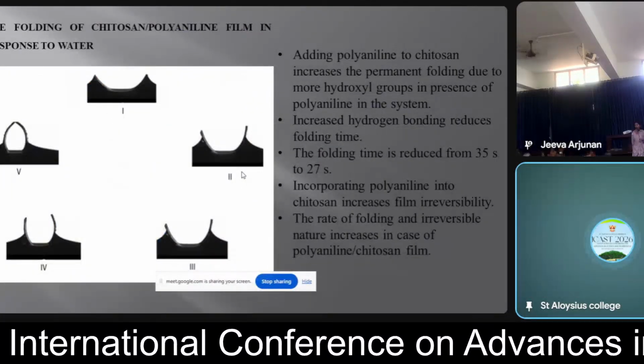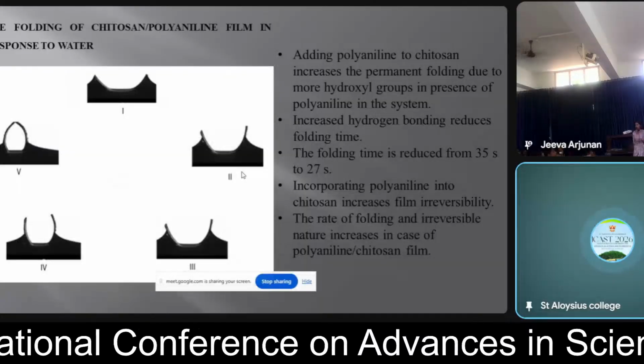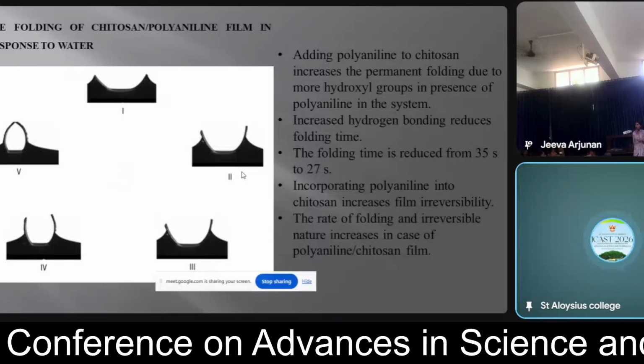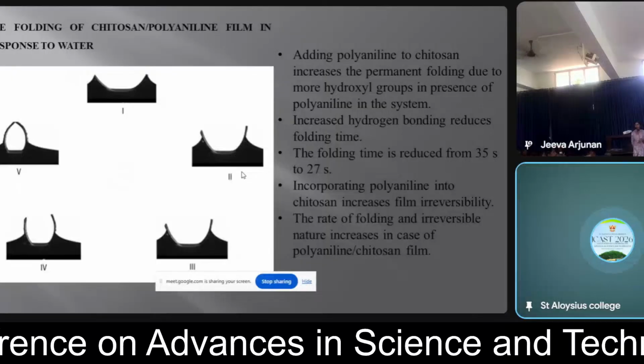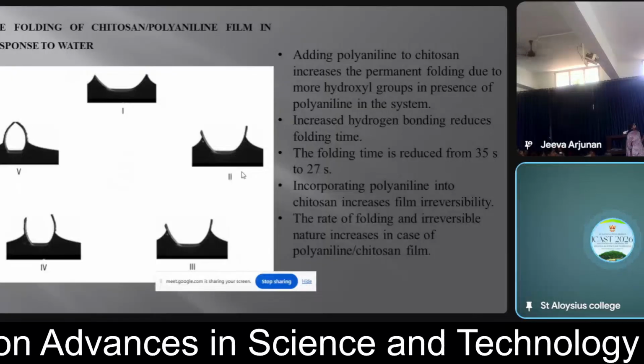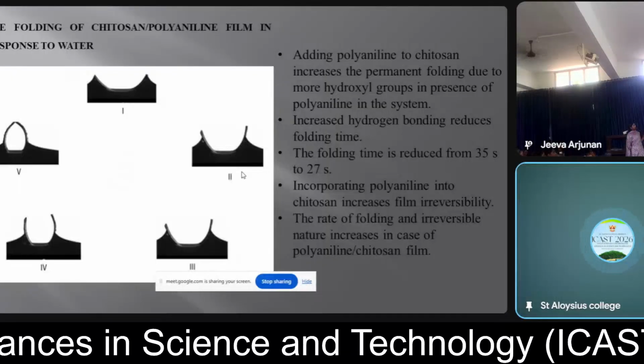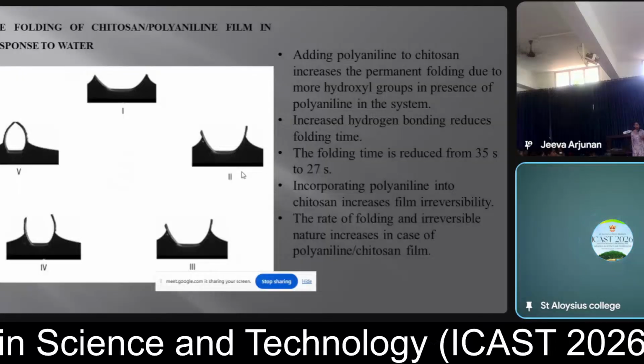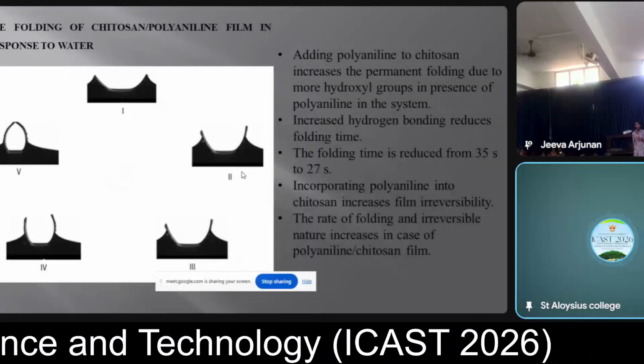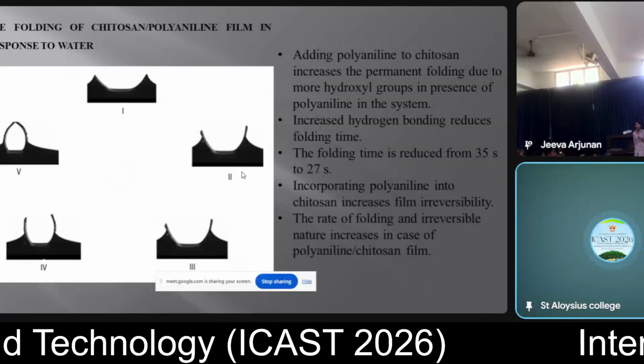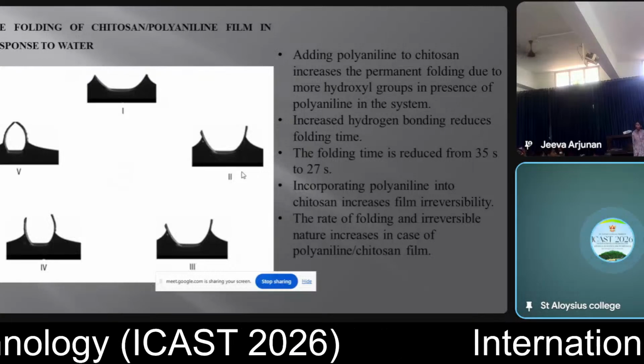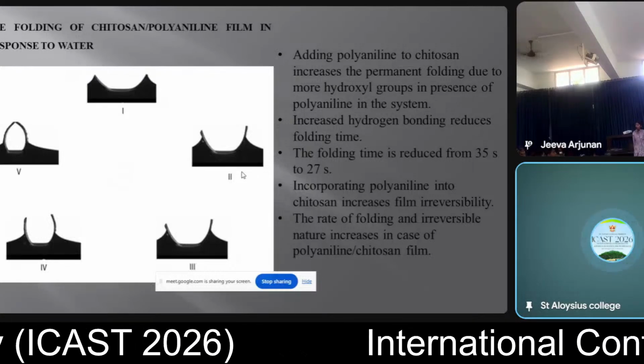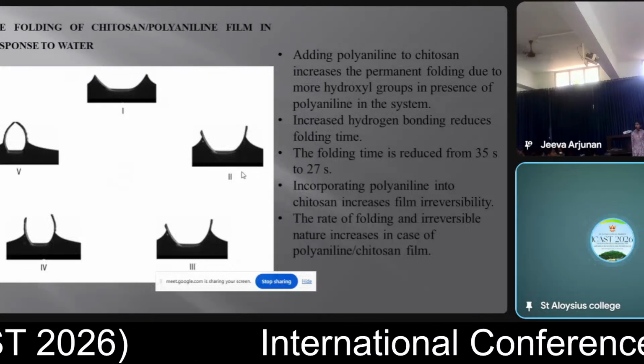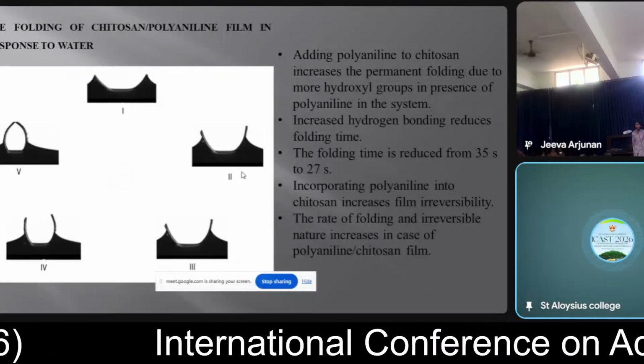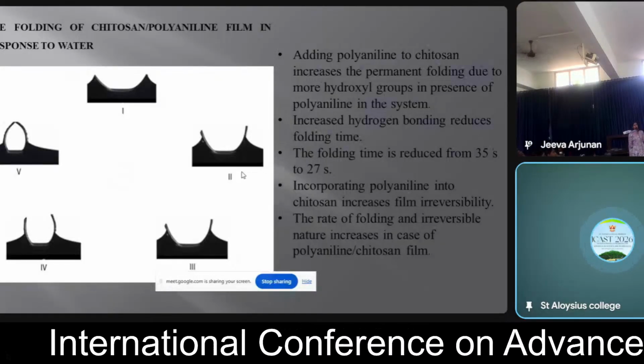So initially, I mentioned the folding behavior of chitosan itself. What happened with the incorporation of polyaniline into it? When polyaniline was added to the chitosan, it started permanent folding. Firstly, it took 35 seconds for the folding, and when we added polyaniline, it was reduced to 27 seconds. It also increases the permanent irreversible nature.